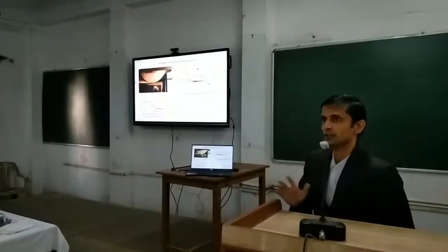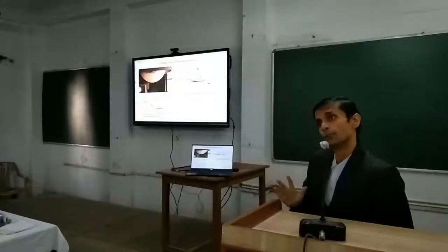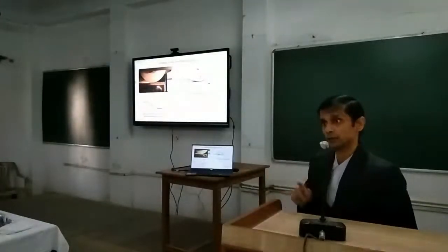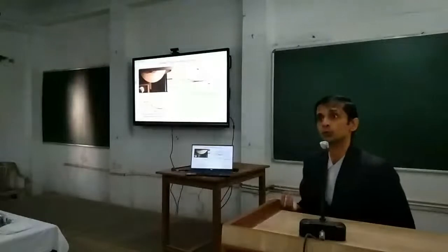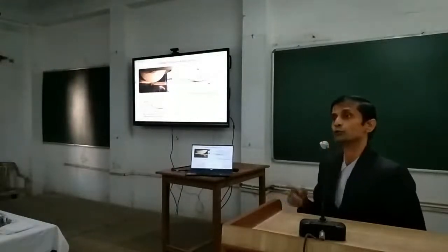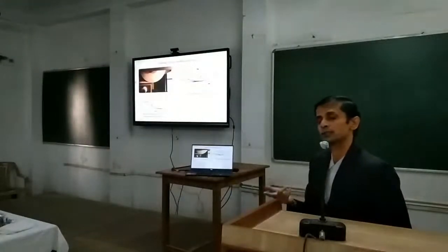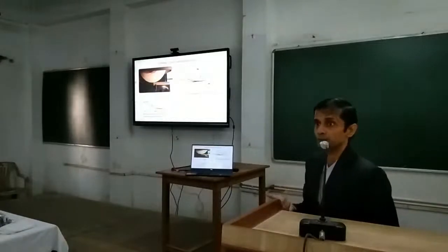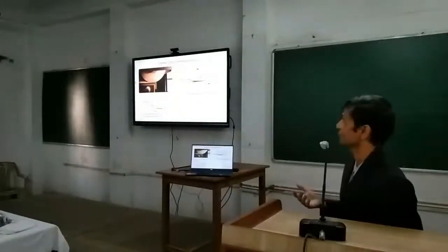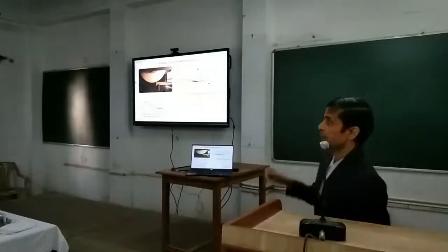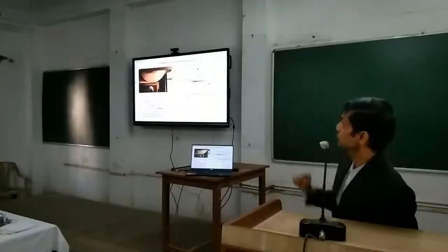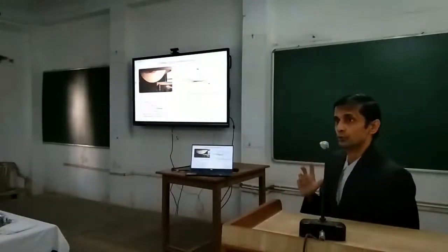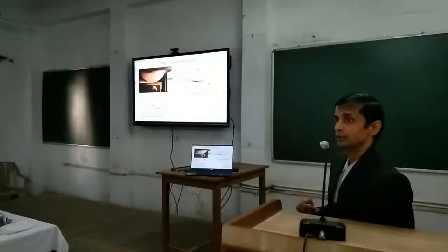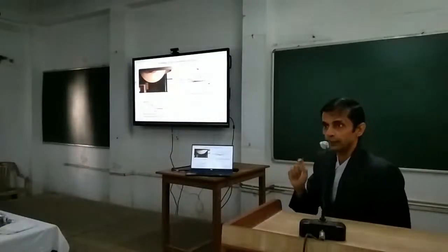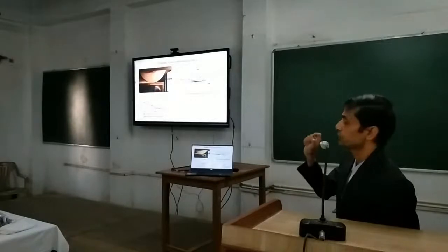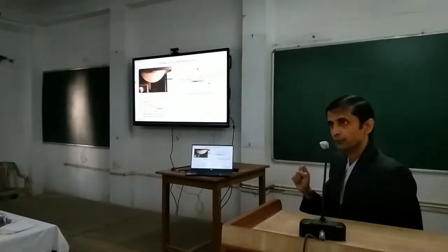high today. Here it is not just 30-40 meters per second; we talk about almost 100-150 meters per second. That means if you convert, 150 times 60, that is almost 9,000 meters per minute. So it's a huge amount of velocity. If you see macroscopically, this grinding wheel is the cutting tool. It is grinding the material. But if you look microscopically, the interaction is taking place between the grains and the workpiece, right?